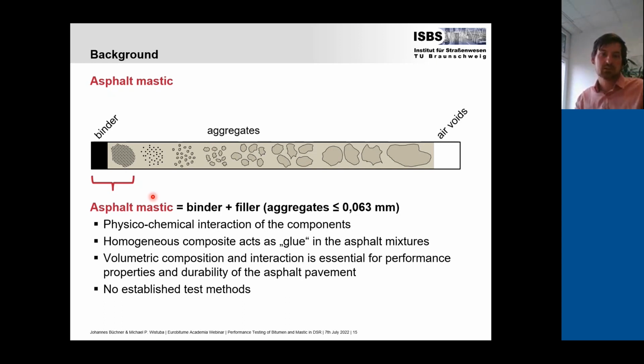So here in our study and in our institute, we defined asphalt mastic as the composite of binder and filler, including all the aggregates smaller than 0.063 millimeters. Asphalt mastic is the composite, as said before, and there's a physical-chemical interaction of both components. Actually, this composite acts as a glue in the asphalt mixture because there's no differentiation possible between binder and filler in the actual mixture. It's a homogeneous composite. The volumetric composition and interaction of both components are essential for performance properties and durability, but there are no established test methods for asphalt mastic.